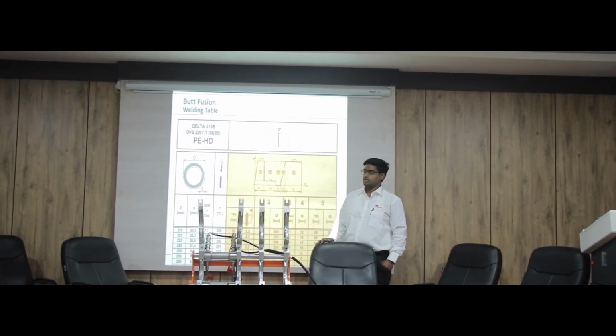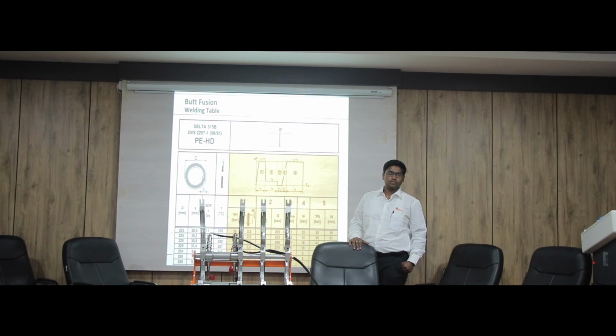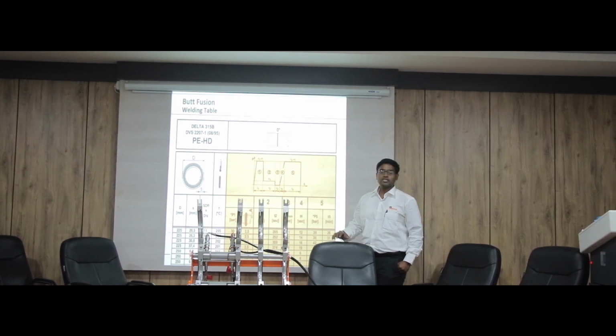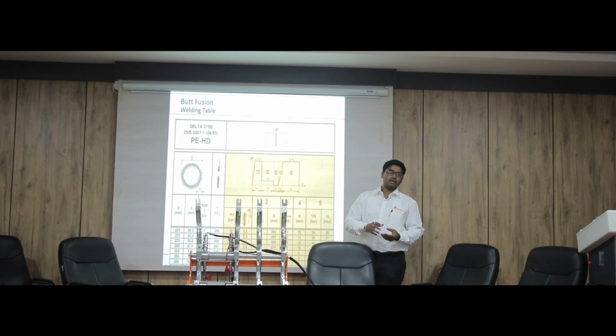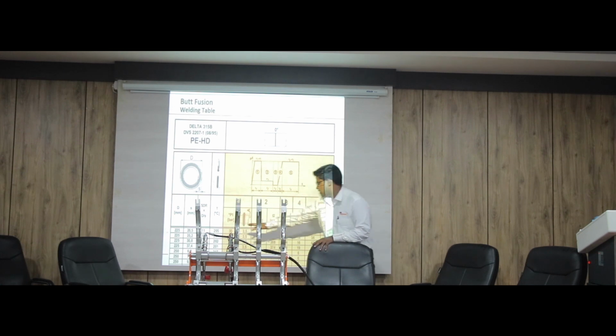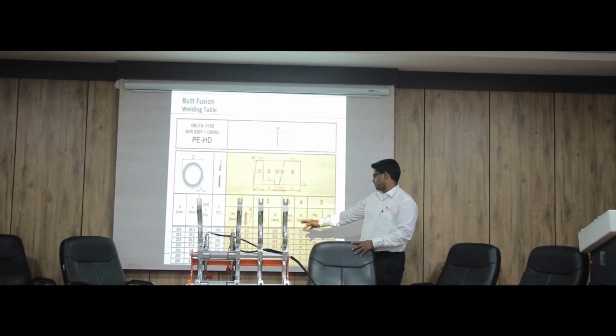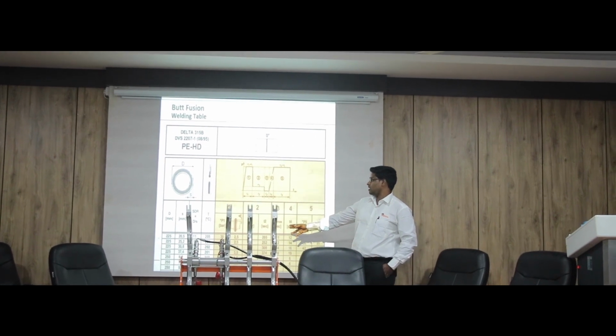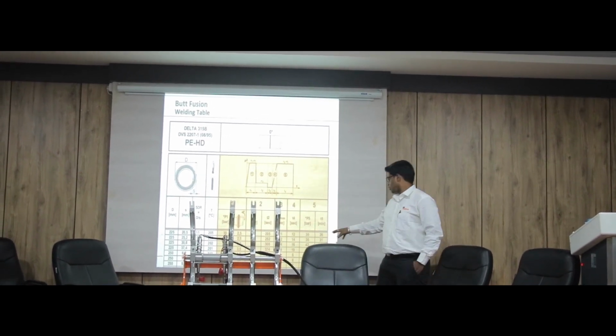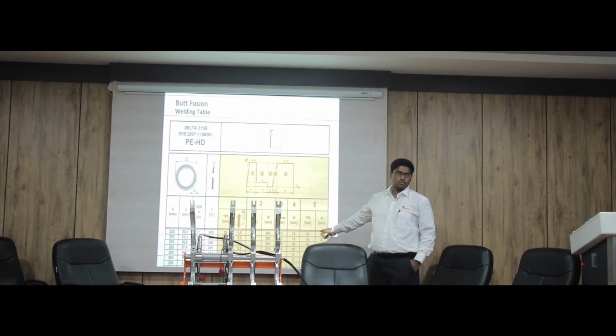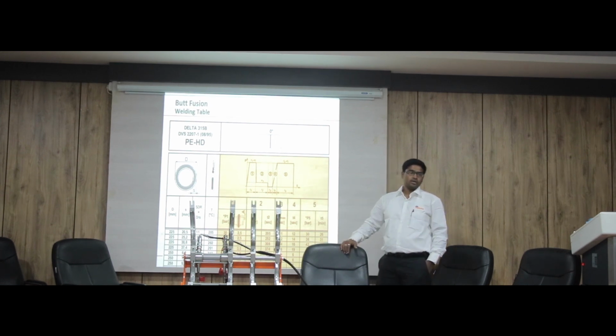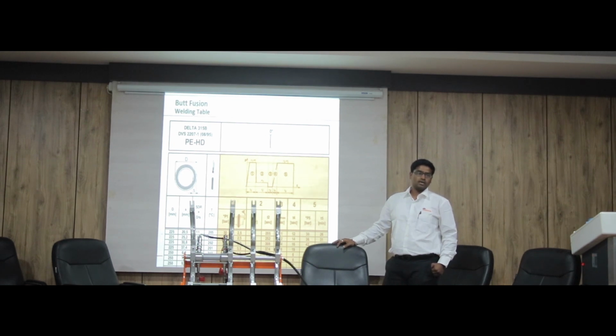And from T1 to T5, how much time will it take? That depends on the diameter and thickness, sir. That varies with the diameter and thickness. Suppose for 225, the total time taken will be like we have 205 seconds for the initial welding, and we have a cooling time of 26 minutes. So it will be somewhere around 30 minutes for a 225 diameter joint. For 110, it will be like half the time. On average, per joint it will be 15 to 20 minutes.